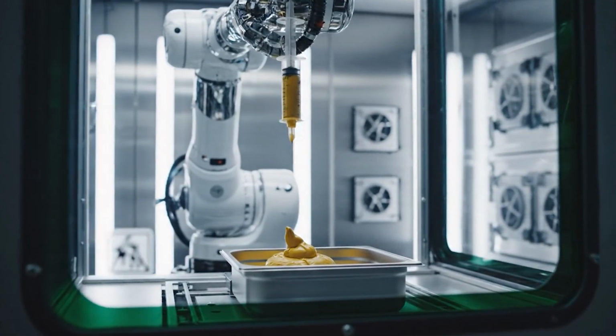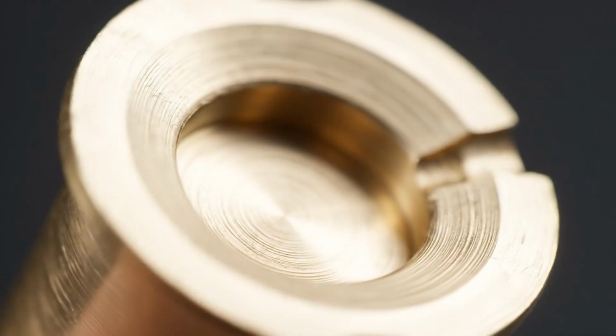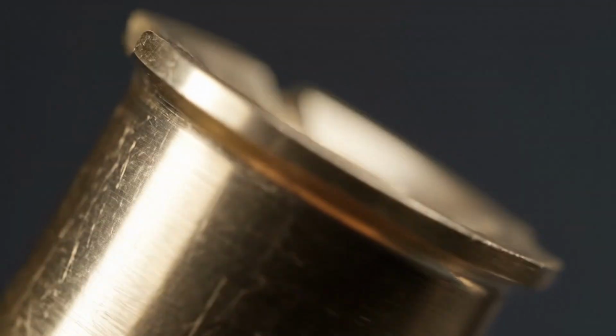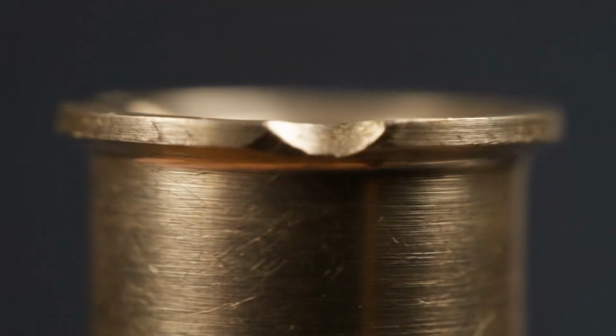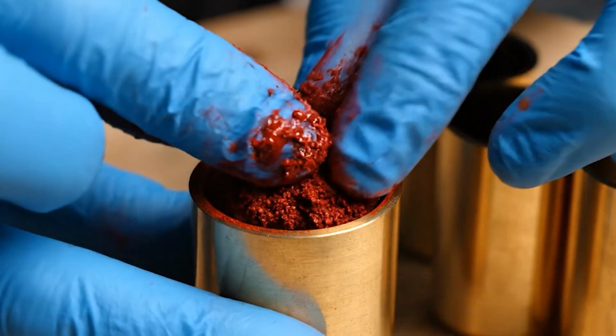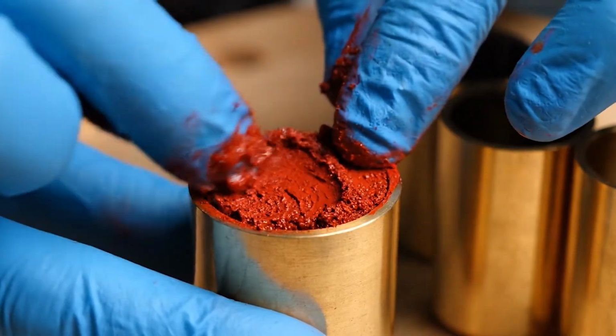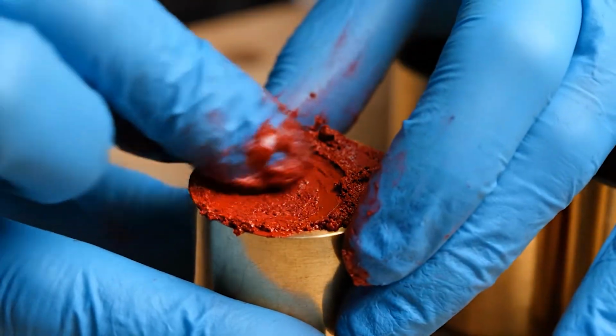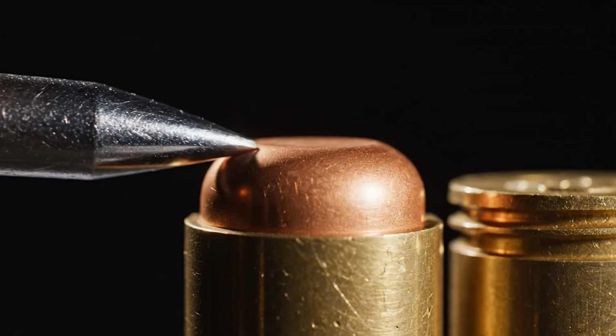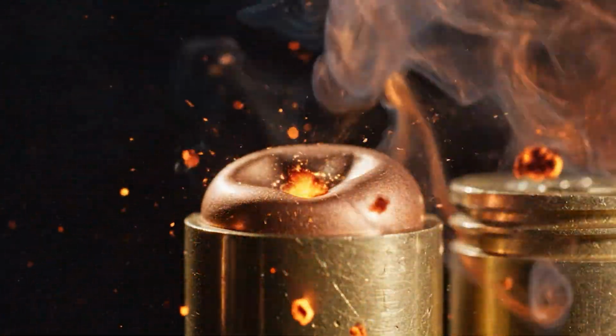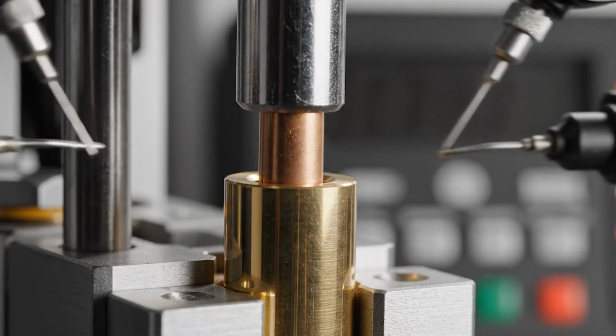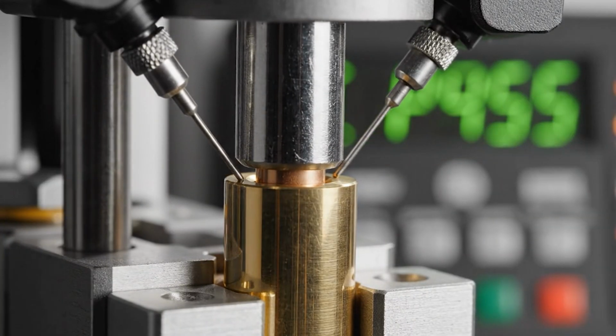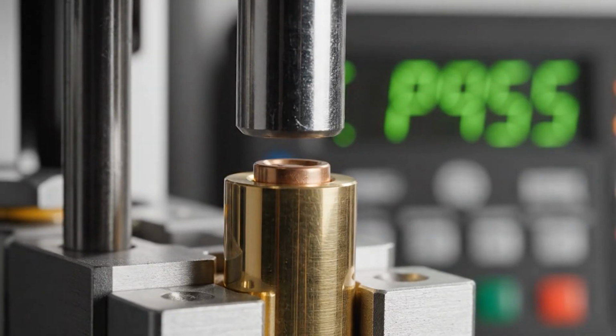The final step for the case is the most critical, the neck anneal. You may have noticed on military ammunition that the top part of the brass looks discolored, showing a bluish-purple rainbow hue. This is not a defect, it is a sign of quality. The neck of the case, where it holds the bullet, must be softer than the base. When the gunpowder explodes, creating 60,000 pounds per square inch of pressure, the neck must expand instantly to seal the chamber and prevent hot gas from blowing back into the shooter's face. But the base must remain hard to prevent the case from rupturing. By heating only the neck with induction coils or gas jets, the factory creates a case with dual properties, soft at the top, hard at the bottom.